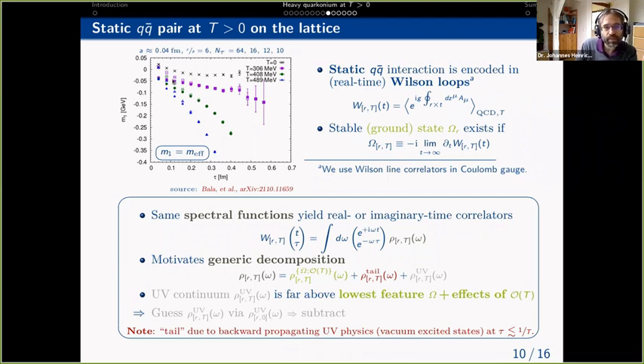Now, with the same lattice spacing, we have different values of T, so different temperatures. And what you see is, as we increase the temperature, this plateau doesn't show up anymore. Instead, it gets steeper and steeper as we increase the temperature. And that indicates that the stable state cannot be there anymore.